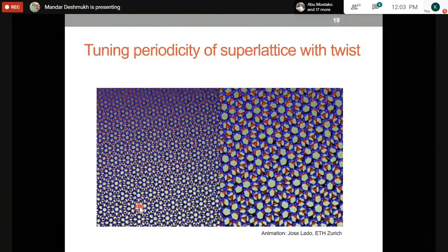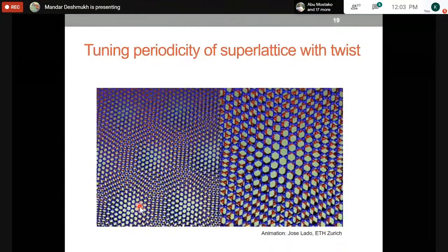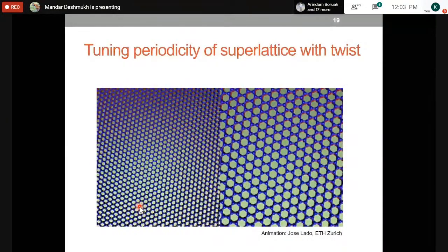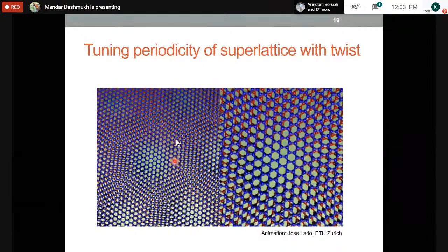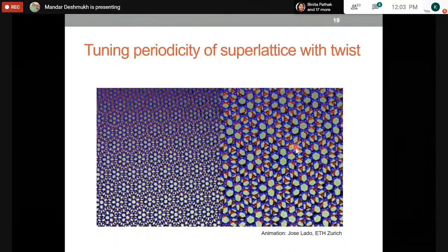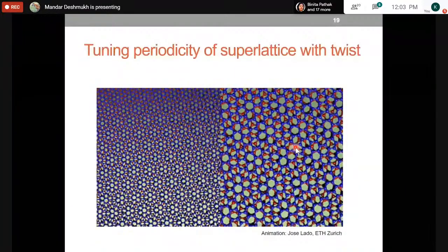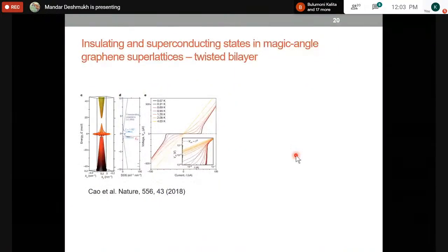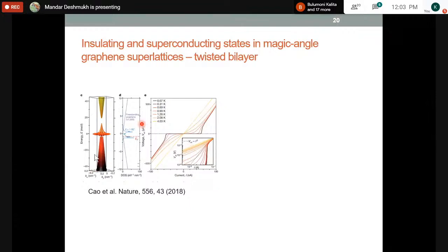Okay, so that means the superlattice that I showed you earlier, which is a lattice which is longer than the atomic spacing, can now be tuned by changing the rotation angle between two layers. And that's a new idea. What people have discovered is that, and this is not our work, we are doing something related, which I'll show you, if you take two layers of graphene and you rotate them relative to each other by 1 degree, you can actually see the superconductivity in 2 layers of graphene.